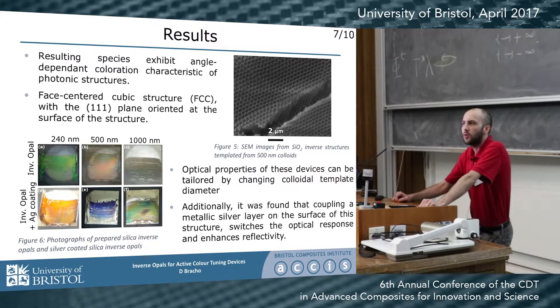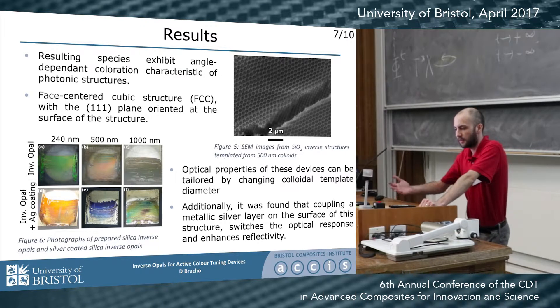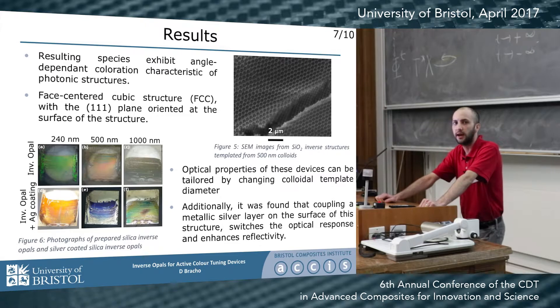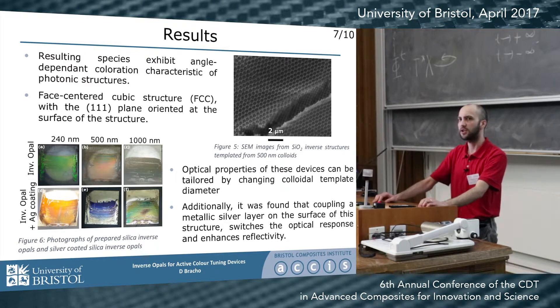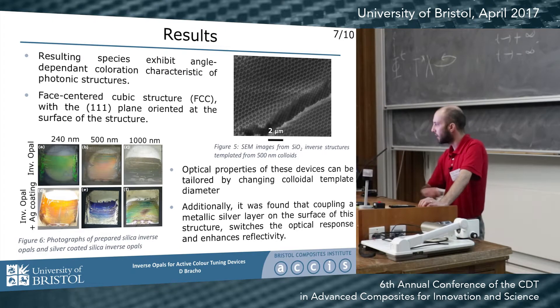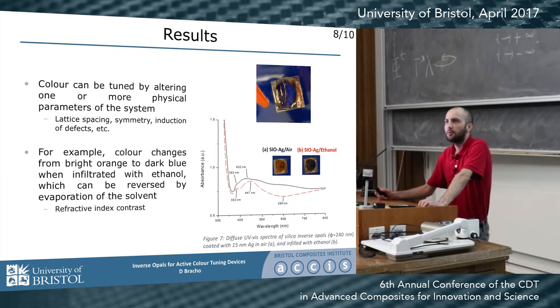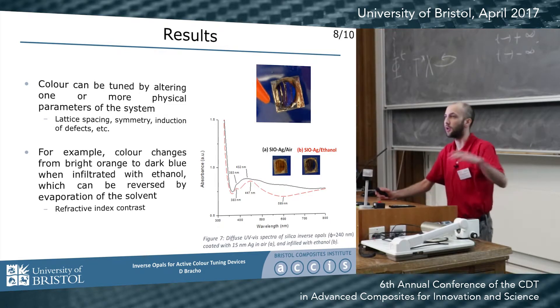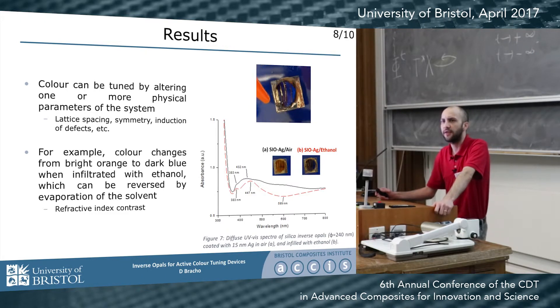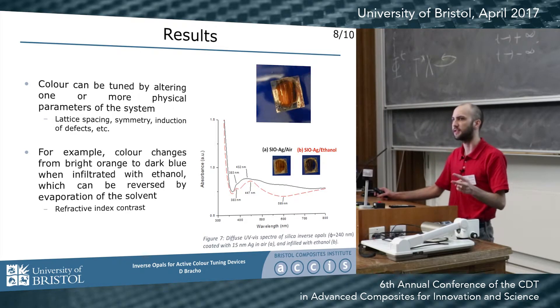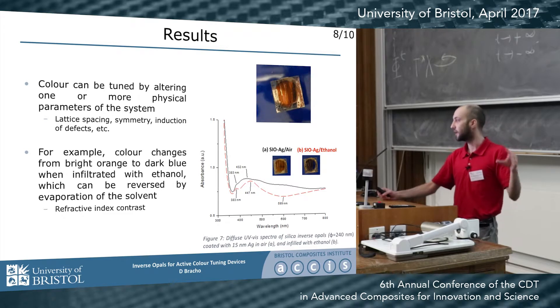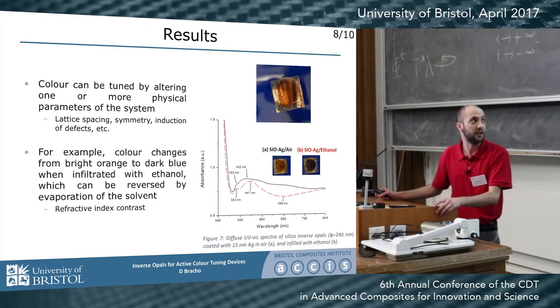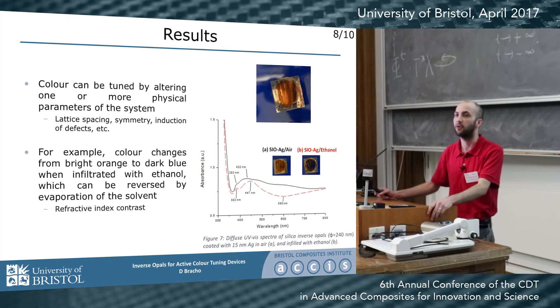It was found that when we sputter coat a metallic layer on top of these structures, for example a silver layer, we see a very important change in the optical properties, probably because of new effects being induced, such as plasmonic resonance in the metallic layer. In terms of color tuning, we were able to obtain a change in coloration. For example, in a 240 nanometer inverse opal powder coated with silver, when we infiltrate the structure with ethanol we are changing the refractive index contrast between the two phases. That results in a change in coloration from a bright orange when the structure is infilled with air, to a deep blue when infilled with ethanol, and we can see that in the spectra as a drop in the 600 nanometer reflectance.